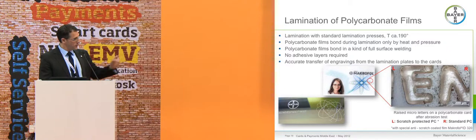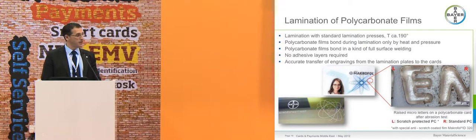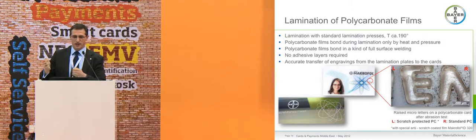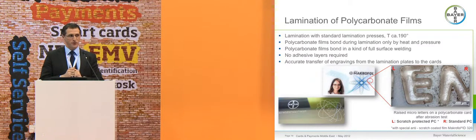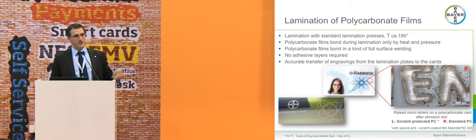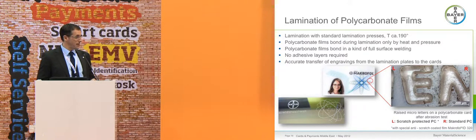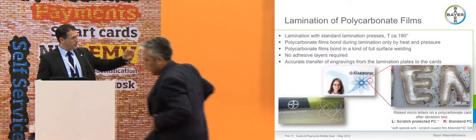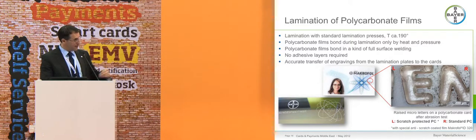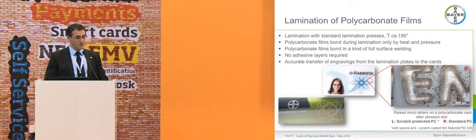What you see also here is that this document is made with the special polycarbonate overlay film that Bayer offers, which has an anti-scratch surface that provides additional advantages during the lamination process because the document surface is less scratch sensitive. That means when opening the cassette after the lamination process, the risk of scratching the big sheet is significantly less compared to a sheet which is not protected. And you can see at the very right side the picture where half of the document is made with an anti-scratch overlay film and the other half with standard. After the abrasion test, see how bad one part of the card looks and how nice the other side, the left side of the picture, where the anti-scratch overlay film has been used.